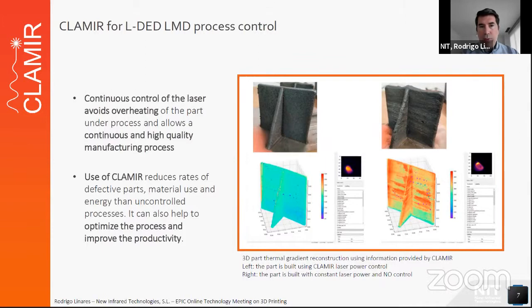It's a very powerful monitoring tool. Here in the images, you can see the 3D reconstruction of the instantaneous thermal gradient of the same part built with control on the left and without control on the right. You can see that without control, there is an accumulation of heat as the part is being built towards the upper layers. And all this, of course, has an impact on the final finishing of the part that is being manufactured. Here you can see the difference between the two parts, with control and without control on the right.